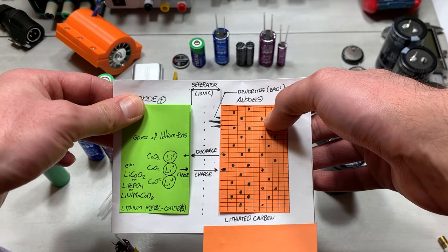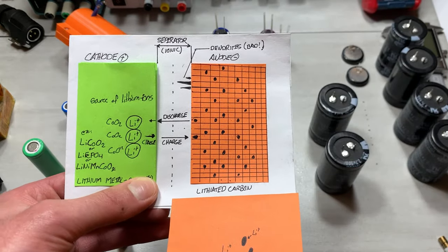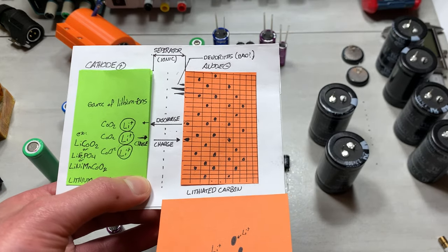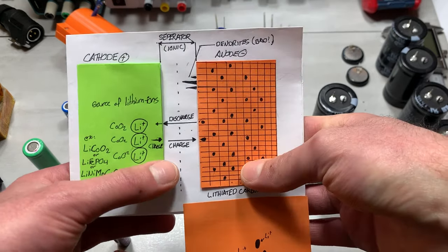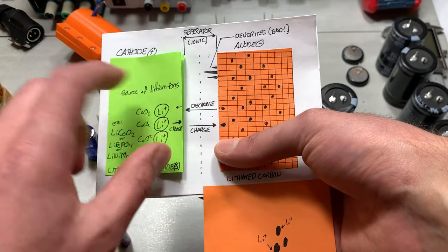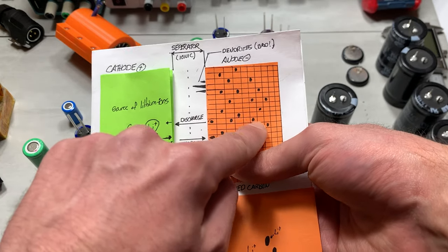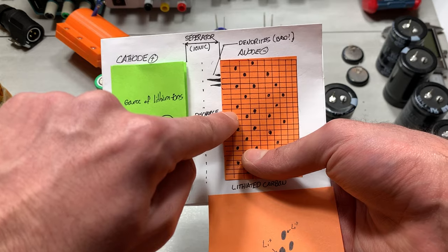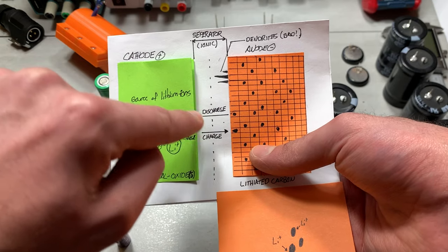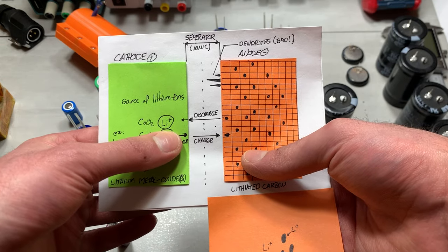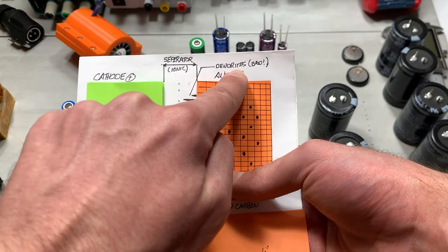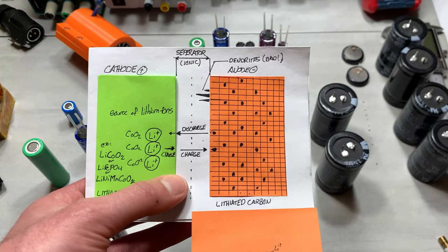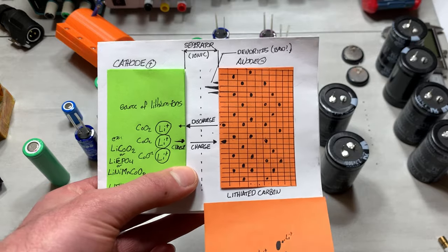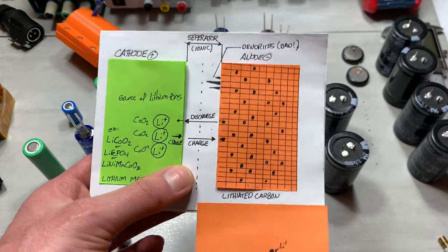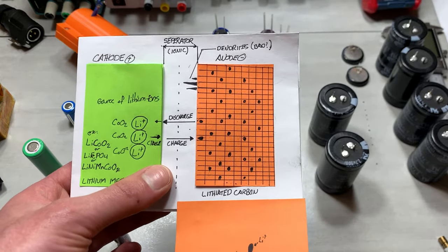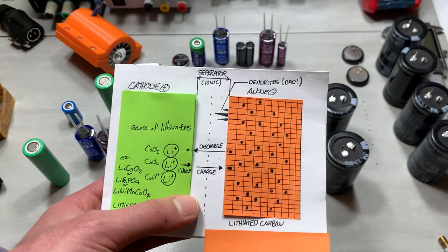and applying a current, and of course not accounting for the losses of efficiency which occur during discharge, will return most of that electrical power back upon discharge, where your lithium ions are taken out of the anode, carried by the electrolyte back into the cathode. And this is where this comes in, dendrites. And this is also where we get into the importance of the separator as far as the durability of lithium ion batteries go, or at least one aspect of the durability.